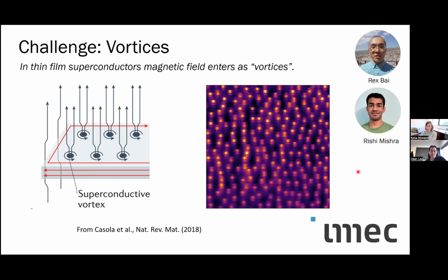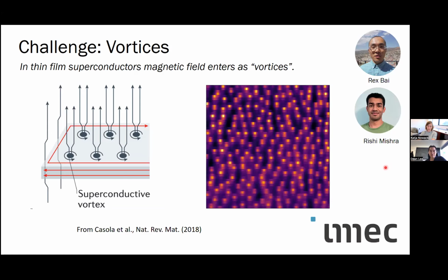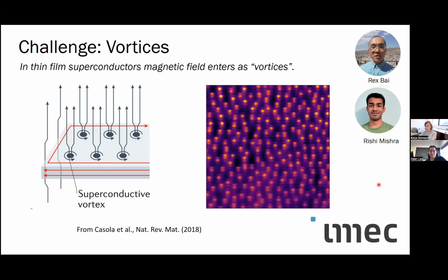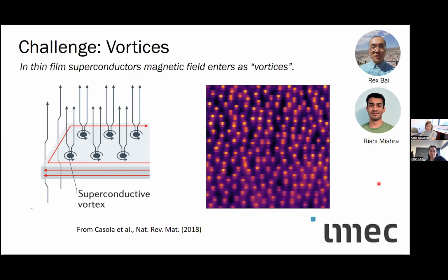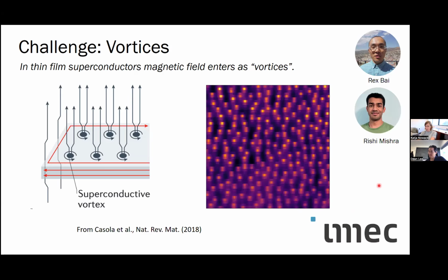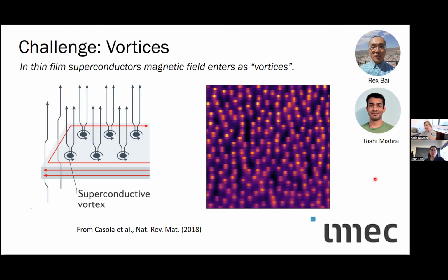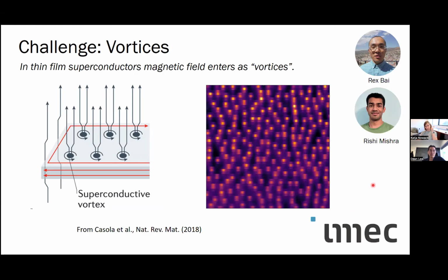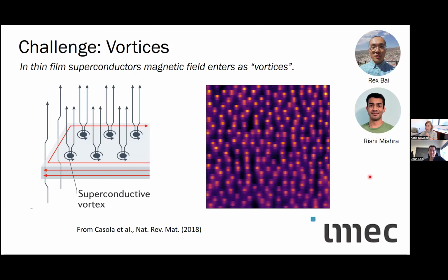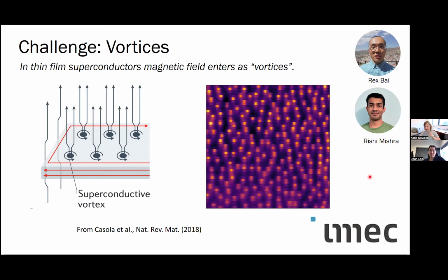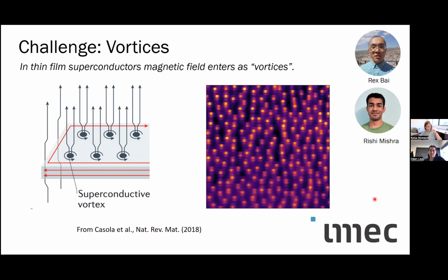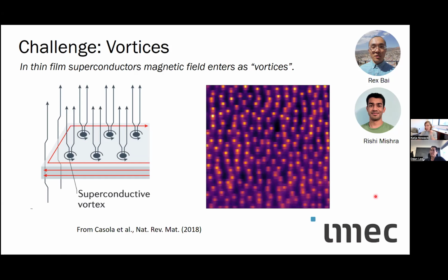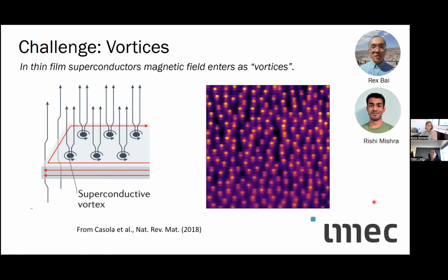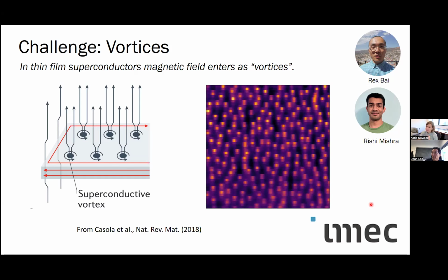And so the vortices are actually a challenge. In these large superconducting circuits, if a vortex gets trapped in a place that's not controlled, because it generates this magnetic field, it can couple magnetic flux into the circuit where it's undesired. And if there's too much magnetic flux coupled into parts of the circuit where they don't want it, it leads to a failure in their logic.